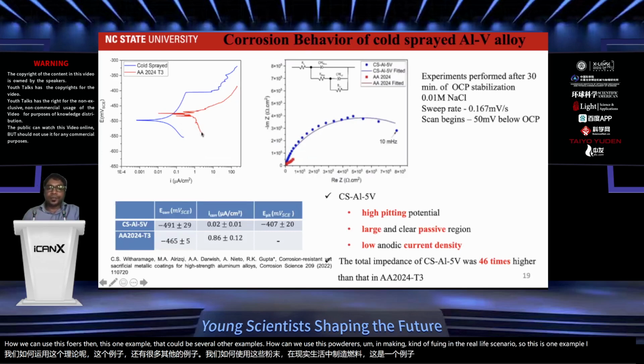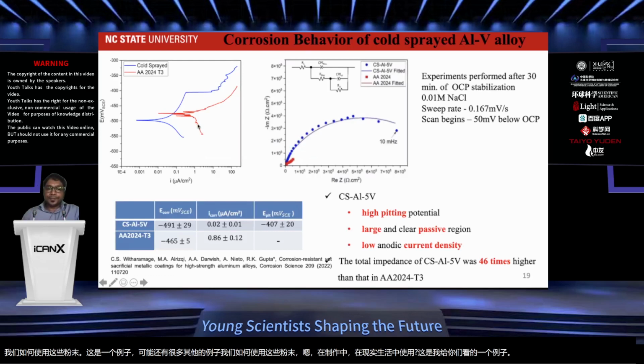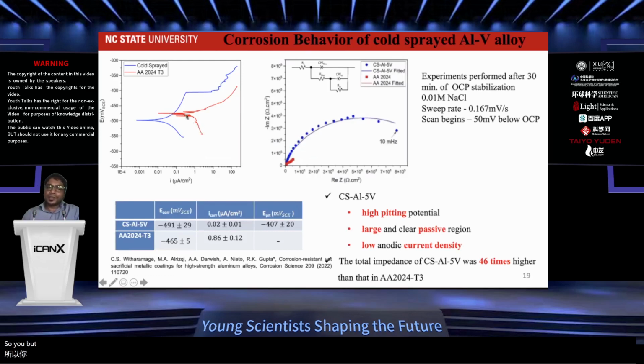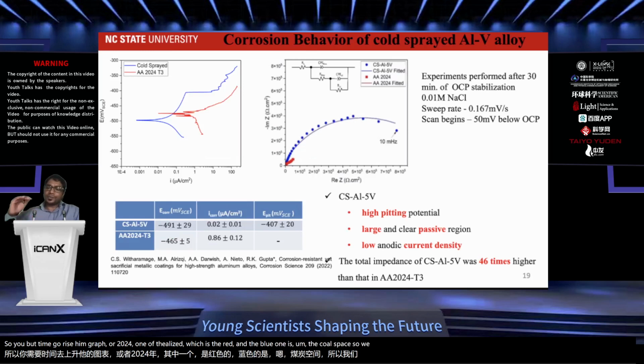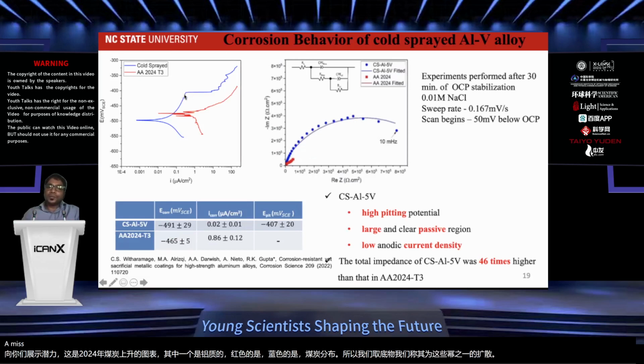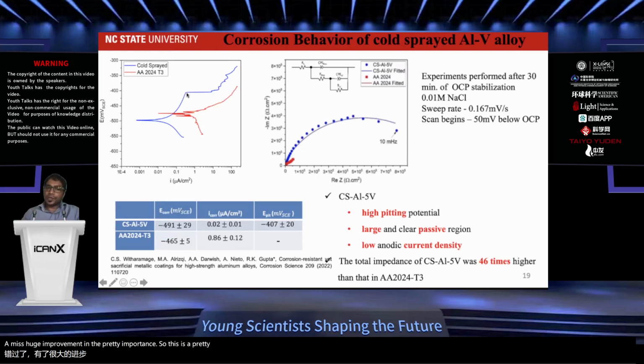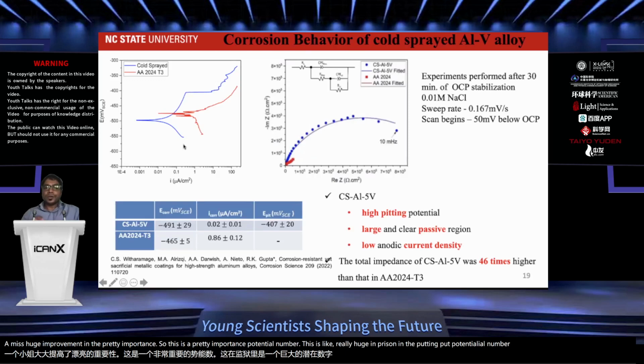I'm showing you the potentiodynamic polarization graph for 2024, one of the aluminum alloys, which is the red, and the blue one is the cold sprayed. So we took the substrate and cold sprayed it with one of these powders we made. And we see huge improvement in the pitting potential. This is the pitting potential number, a really huge increase. So by these coatings, you can get really high corrosion resistance.